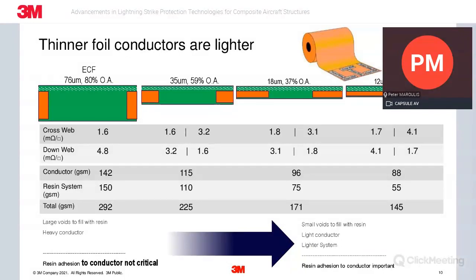So if you look at lines 3 to 5, from the conductor weight of 142 grams per square meter to 88 grams per square meter, and for the resin system from 150 grams per square meter to 55 grams per square meter. So some significant overall weight savings here for the potential of this type of solution.